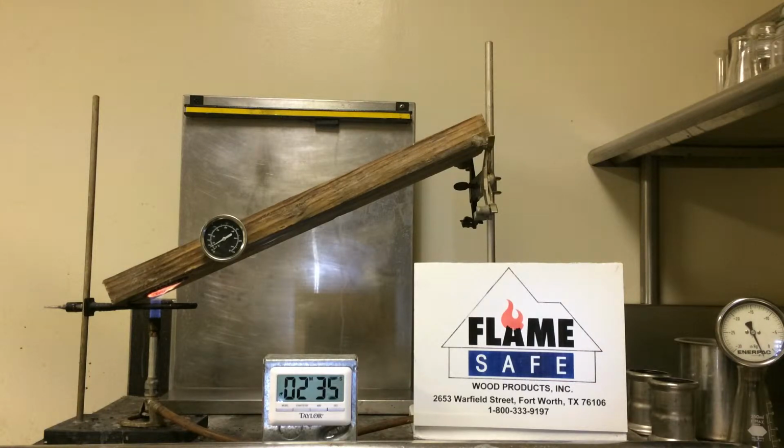The water used for the water exposure of each cycle was accumulated in a tank below the specimen. The water was not recirculated. The specimen was dried in a gas-fired, forced-air kiln at a temperature of 136 degrees Fahrenheit to 138 degrees Fahrenheit, measured 1 inch above the surface of each panel. The air movement above each panel was maintained at 72 feet per minute, measured at the center line longitudinally. At the end of each cycle, the position of each panel was reversed within the apparatus and rotated 180 degrees.